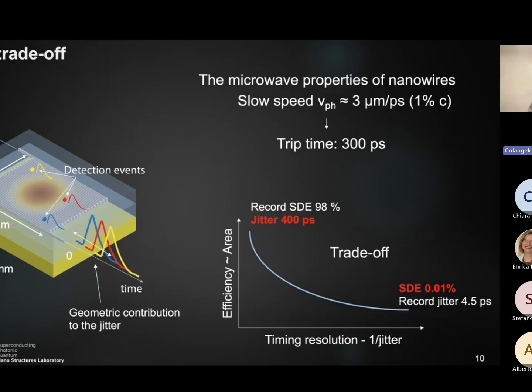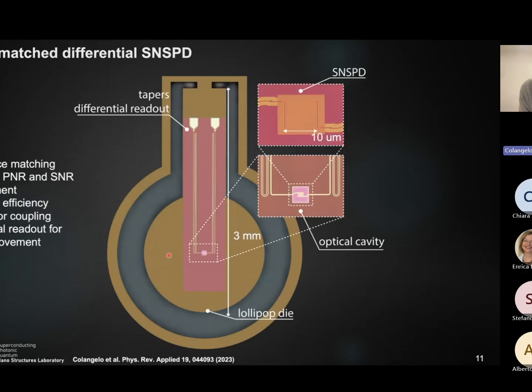So there is, and I introduce to you what's called the impedance-matched differential SNSPD, which is something that I did during my PhD. So this is a revised architecture of the SNSPD. You can see that this is actually a picture of the real device. This is a lollipop-shaped die, and it's lollipop-shaped because we use it for self-aligned coupling. So this is basically the same diameter as a ferrule of an optical fiber, and it's self-aligned because the mode is directly projected onto the area of the SNSPD through the optical cavity.